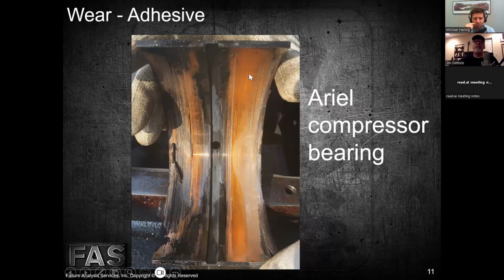Yeah, so these bearings, I think we covered bearings in the first podcast or the second podcast we did, but these bearings have multiple potential layers of materials, often starting with a steel back, and then an aluminum layer bonded to the steel back, and sometimes a copper or a nickel bonding or diffusion layer on top of that. And then oftentimes a Babbitt or something like an LTO or a lead tin copper overlay on the top of that surface, and then sometimes a tin flash coating on top of that.